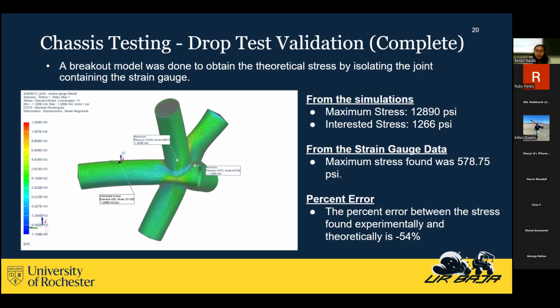One of the reasons I think there is a 54% error is the fact that, consistently in our drop test, the front wheel always hits the ground first before the back wheel does. So it doesn't necessarily experience the whole 3G drop that we assume from our initial drop test FEA. That's one of the big reasons why I think there is that 54%. Also, we don't account for the shock loading. How does the shock itself absorb all the G's from the chassis itself? Okay.